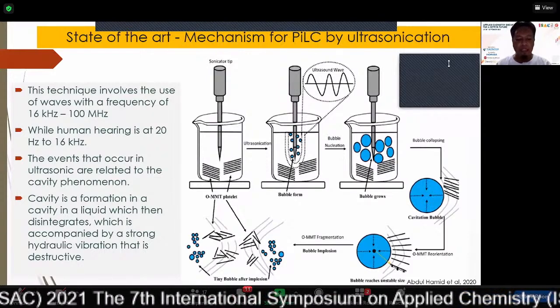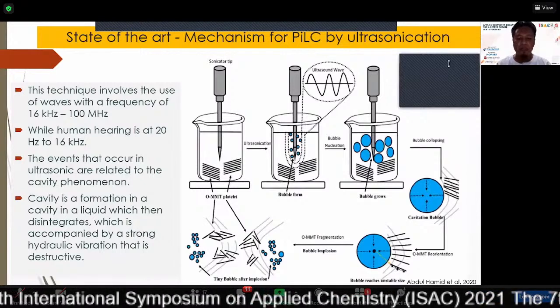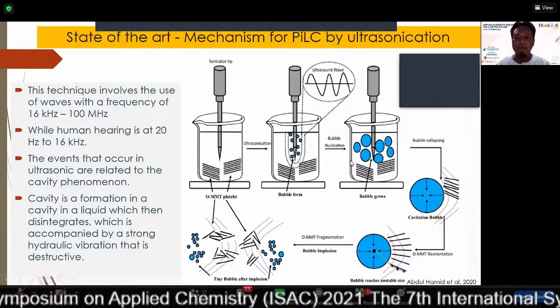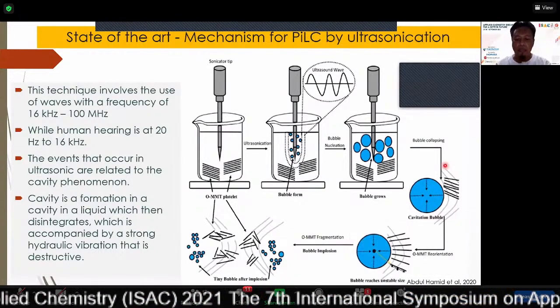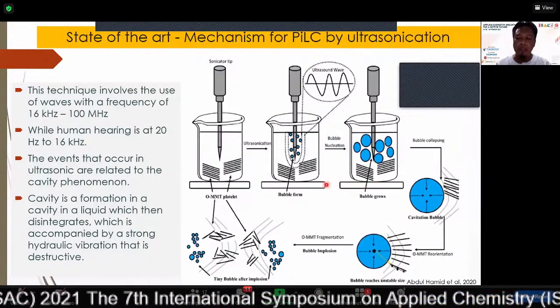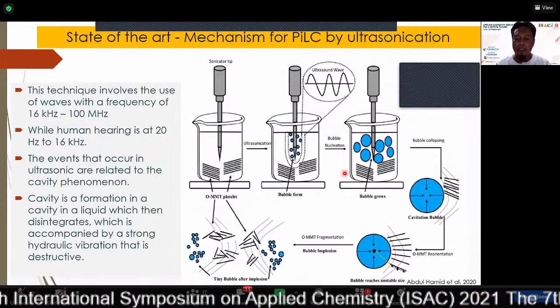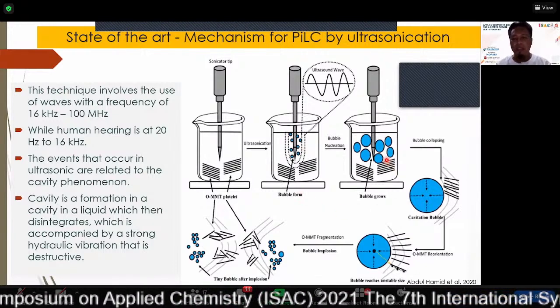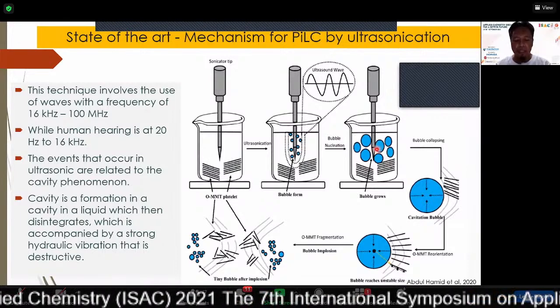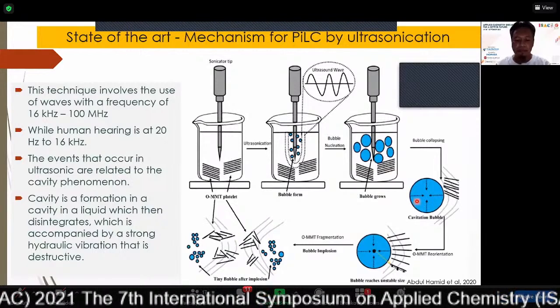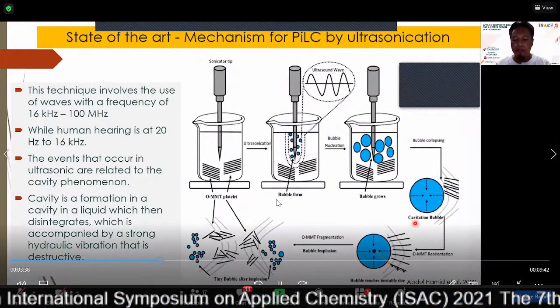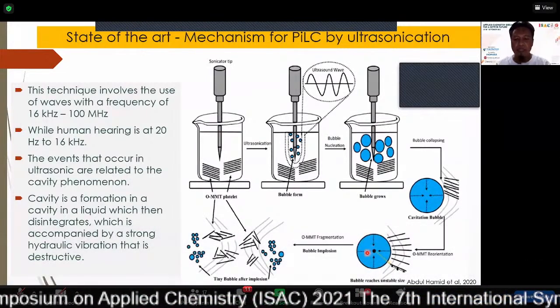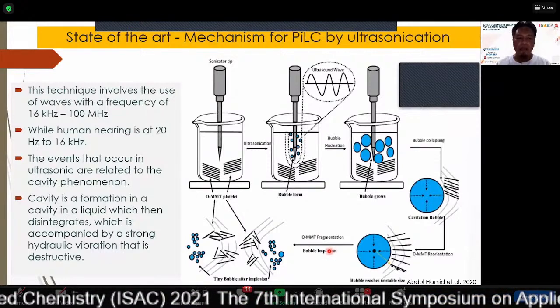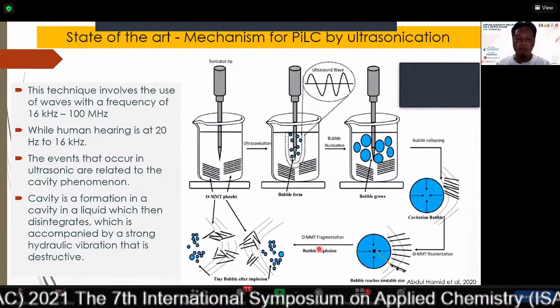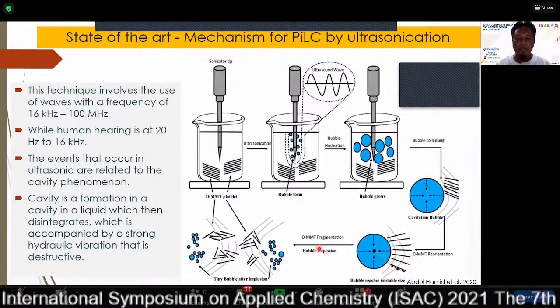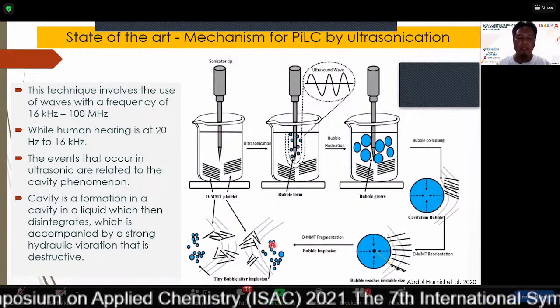In the right picture, you can see when the liquid is irradiated by a strong ultrasonic wave, a large quantity of tiny gas bubbles appear and collapse violently. This phenomenon is called cavitation. The tiny bubbles repeatedly expand and grow according to the pressure of the ultrasonic wave. The speed of bubble collapse sometimes increases, and the strong hydraulic force of the bubbles penetrates metal oxide nanoparticles into the interlayer spacing in the layer structure of the clay.